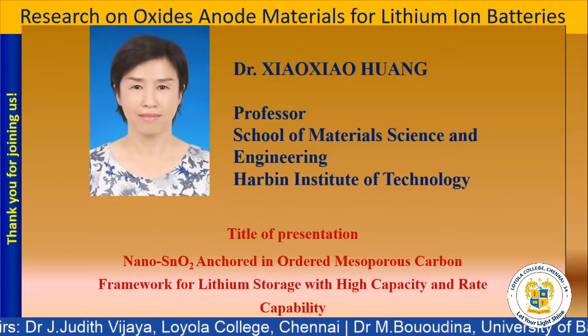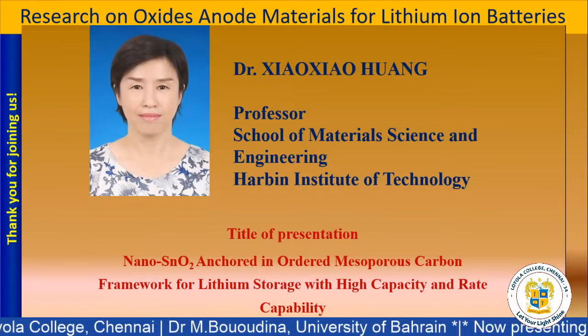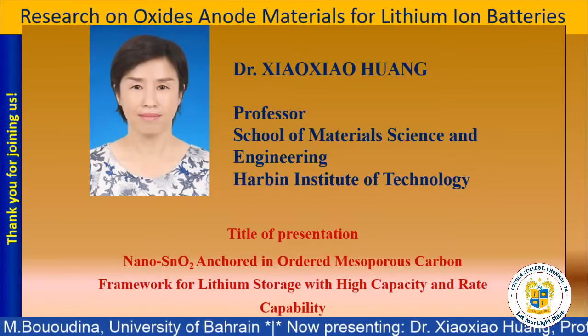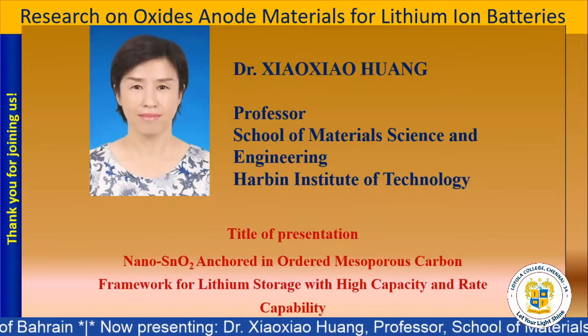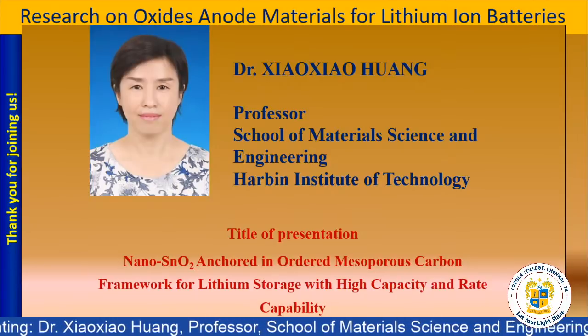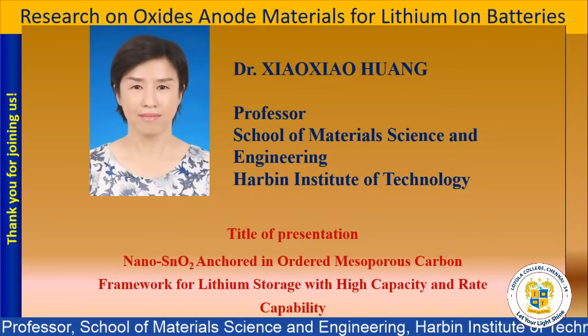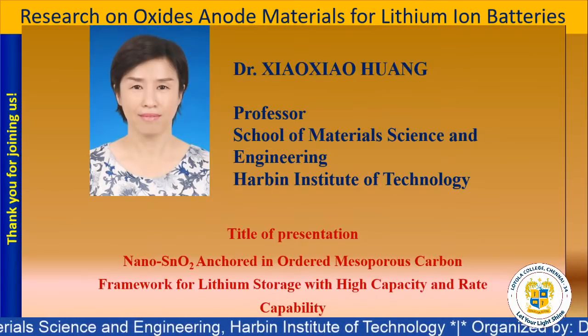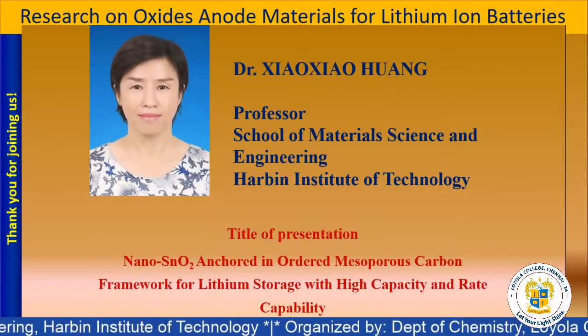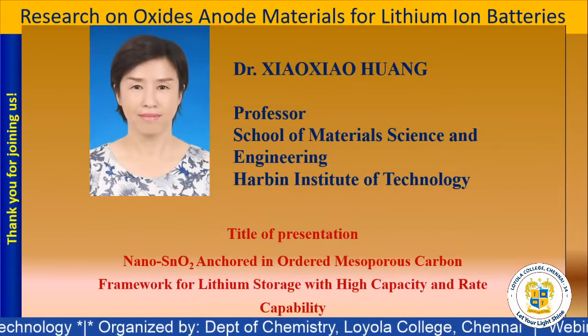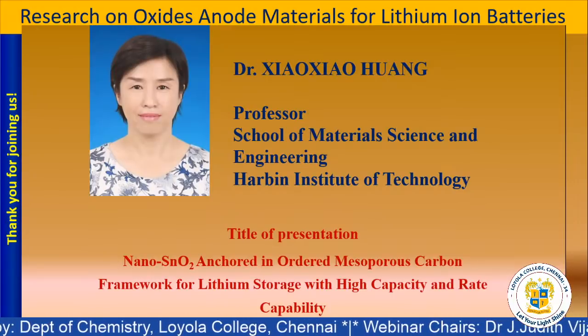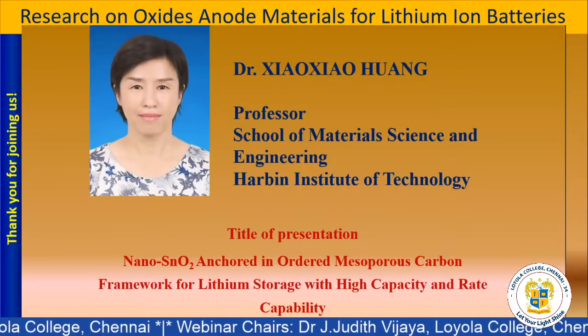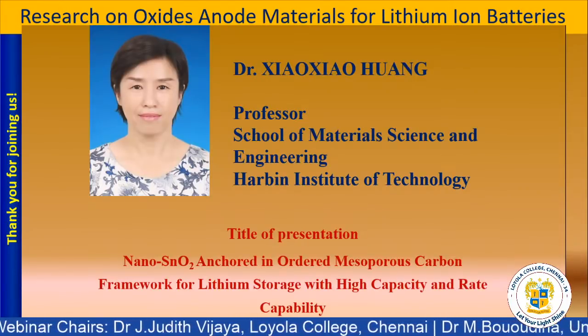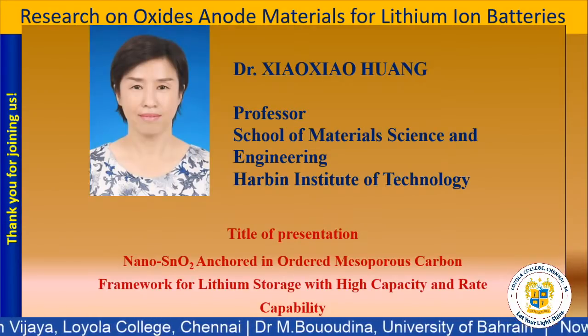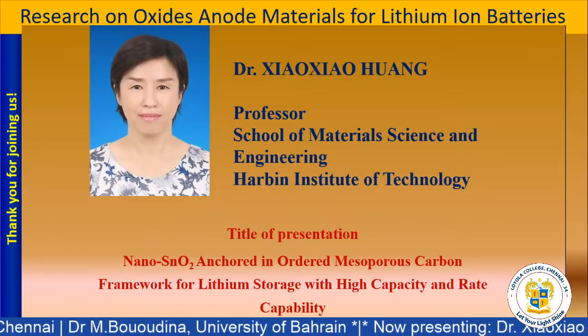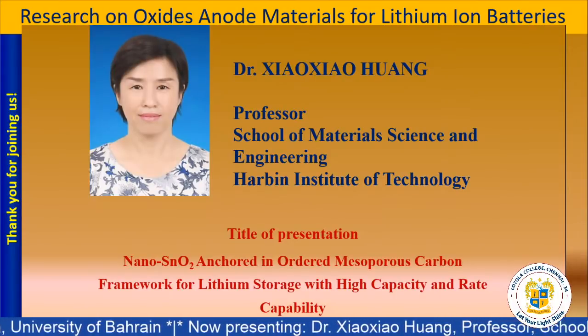The 10th is: will the gel precursor reduce the conductivity of the metal oxides? No. We use the polymer precursor in the gel to produce the gel, and we put the gel in the oven for heat treatment, and then the precursor will transform into carbon, and the precursor will form the metal oxide. So if we use the carbon precursor in the material, it will be better. It will be used for the conductivity improvement.